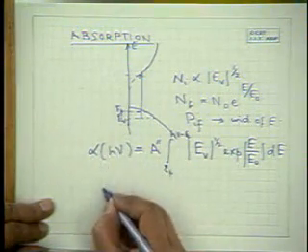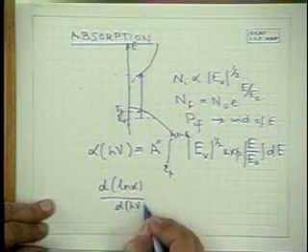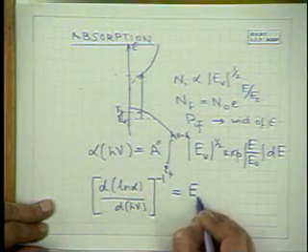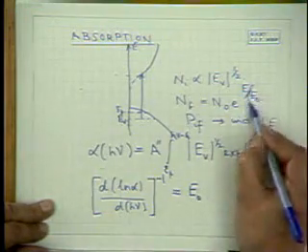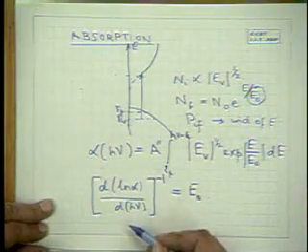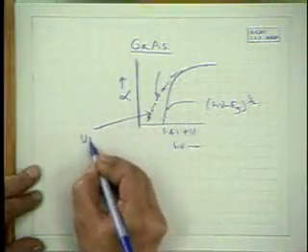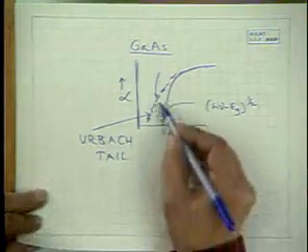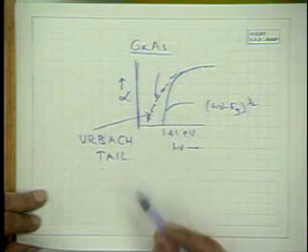And if we calculate d log alpha d h nu, the slope, it can be shown that the inverse of the slope is equal to E0. So this E0 is an experimental parameter which is related to the inverse of the slope of the optical absorption edge. And this tailing is known as an exponential Urbach tail in the optical absorption edge, which is seen in many semiconductors when you have heavy doping effects.